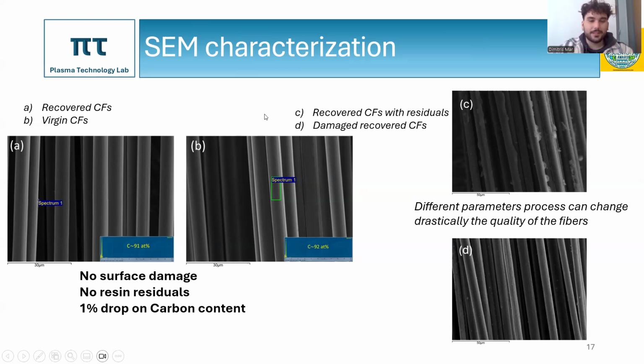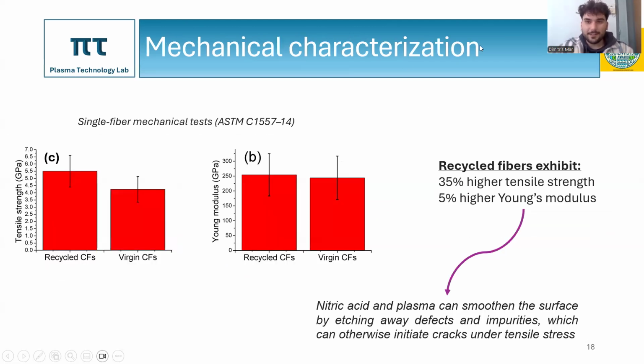But in order to achieve those good results, we need to test various different parameters. And we saw that different parameters of the process can change drastically the quality of the fibers. For example, you can see in figure C some recovered carbon fibers with many residuals on the surface that come from a batch with a too low concentration of solvent. While on figure D, you can see some damaged recovered carbon fibers that come from a batch with a too high power input. We did some mechanical characterizations, specifically single fiber mechanical tests, and we saw that the recycled fibers exhibit 35% higher tensile strength and 5% higher Young modulus compared to the virgin fibers.